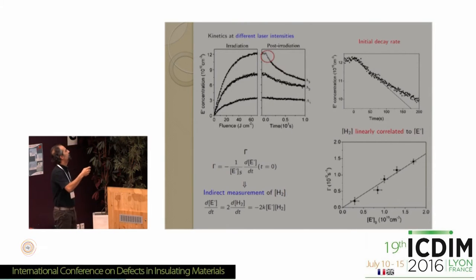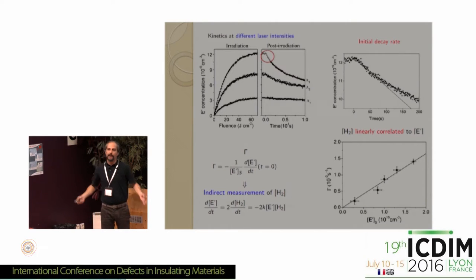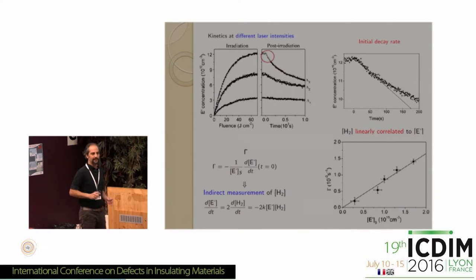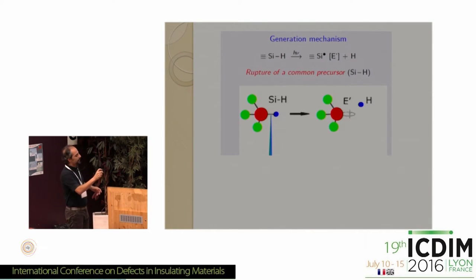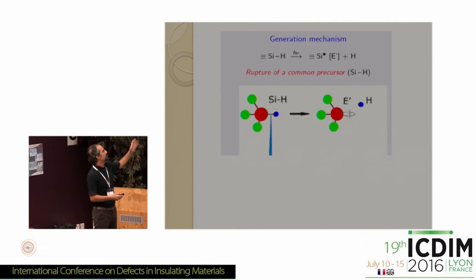And then we showed that the concentration of hydrogen is linearly correlated to the concentration of E prime, which means that they need to come from a single process if their concentrations are always correlated to each other. So the picture that comes from these studies is the following. You have these impurities, you break photochemically SiH bonds, you generate silicon dangling bonds and hydrogen atoms.